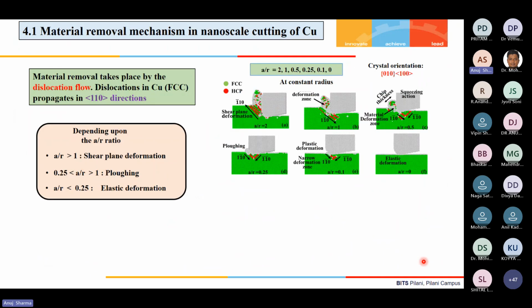So after validation, I studied the material removal mechanisms for nanoscale cutting of copper for different parameters, for different A/R ratios, varying from 2 to 0. And it showed that the material removal took place by dislocation flow. These are the dislocations which are flowing, and they propagate in 110 directions.